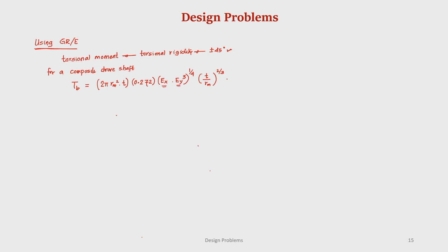Therefore, there must be lamina which have stiffness in the y and x direction. So, it comes from 0 degree and 90 degree lamina. So, we must have 0 and 90 also. For shear, we must have plus minus 45. For this critical torsional buckling, we must have 0 and 90, more importantly 90. Also, for a composite drive shaft, the first natural frequency of bending vibration is pi by 2 under root E x I by m L 4. Therefore, you can clearly see that the first natural frequency depends upon E x.